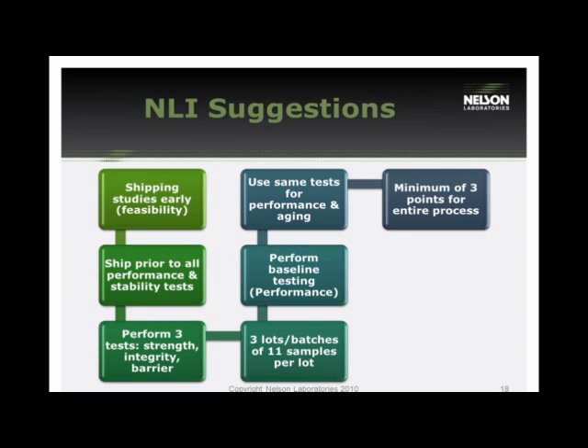After the feasibilities and you've worked on your sterilization, you want to start working towards performance and stability testing. In performance, you're going to do three tests from separate categories, including strength, integrity, and microbial barriers. You're going to use their sample sizes, three lots of 11, and then you're going to move into baseline testing. Baseline testing is going to evaluate what your package looks like when you've manufactured it and if it goes straight to the customer. After that, you're going to want to move into accelerated aging. Accelerated aging is going to evaluate the same tests at the end point of your stability. So encompassing all of that, you want to make sure you do a minimum of 3 points for this entire process.